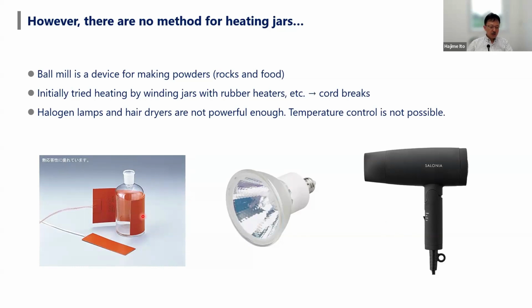So we tried to heat up the ball milling jar using a heater, but the connection was not very good and would easily break after the reactions. We also tested a lamp and a hair dryer, but the hair dryer was not powerful enough for heating up the ball milling jar.